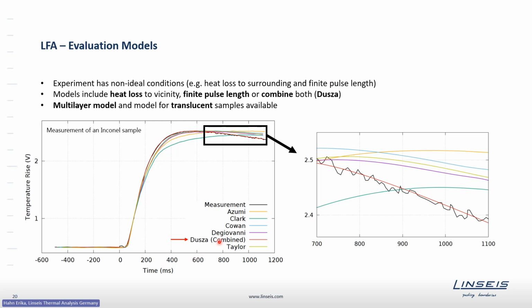As mentioned, there are many models available, modeling this heat loss or the finite pulse length effect. Typically, most of the models just focus on one. The unique part about Linseis is that we have the combined model by Dr. Dusza, who combined both effects into one model, simultaneously fitting both effects. This is, let's say, more or less a universal model, which can be applied to very many samples. In addition to that, we also have a model for translucent samples or for samples consisting of several layers, up to 2 or 3 layers.